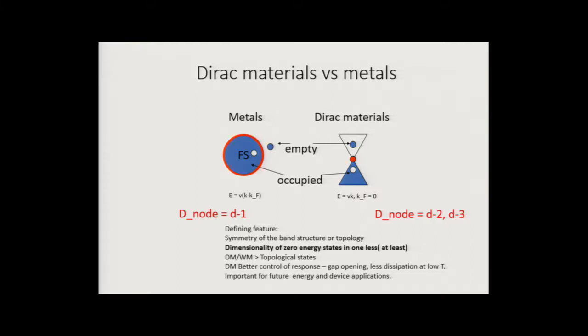So there is typically a symmetry that allows these terms to cross. And that's what the utility of Dirac materials could be. If you have a symmetry that allows me to open and close the gap, then I can take advantage of the symmetry. I can functionalize the response of a Dirac material by closing and opening or drastically changing the properties at the nodal point. So the symmetry for graphene, for this conversation, let me say that you have an A-B sublattice symmetry that forces a degeneracy point.